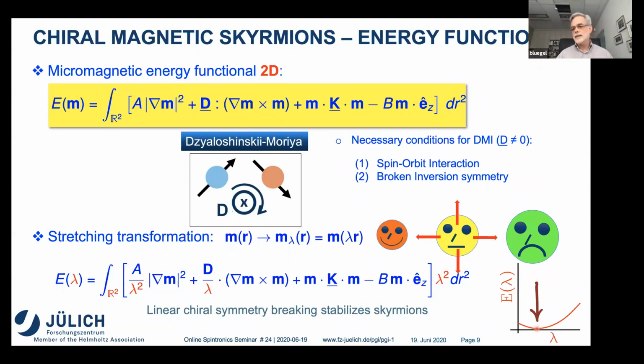But from this analysis, we can actually learn quite a bit. So what you see is, if the Dzyaloshinskii-Moriya interaction is small, if D, the strength of this Dzyaloshinskii-Moriya interaction, is small, we expect the minimum at very small lambda. That means a small Dzyaloshinskii-Moriya interaction gives you small skyrmions. This is sometimes confusing because sometimes people think large Dzyaloshinskii-Moriya interactions give you small skyrmions. No, you see, if there is no Dzyaloshinskii-Moriya interaction, the skyrmion collapses. So a small Dzyaloshinskii-Moriya interaction gives you a small skyrmion.